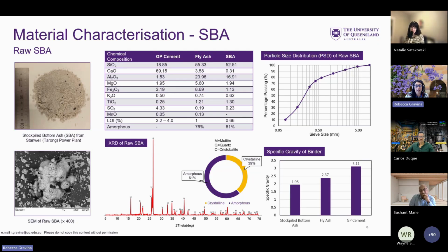In terms of the XRD analysis, we can see that the stockpile bottom ash has 61% still in the amorphous phase, as opposed to 39% in the crystalline phase. So the higher the amorphous percentage that you have, the more reactive that material will be when we are developing the concrete mixes. It is a little bit less for the stockpile bottom ash than what we would experience with the fly ash, but there are ways we can work around that. And also the specific gravity of the stockpile bottom ash is slightly lower than that of the fly ash.